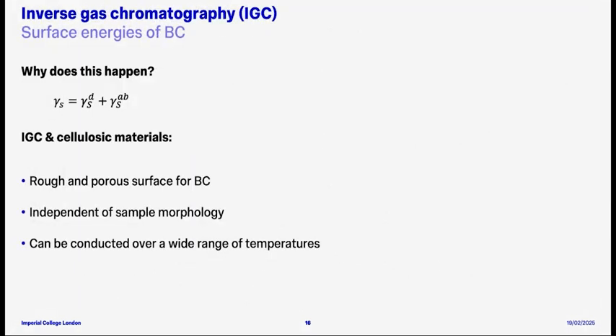So to investigate this observed difference in the quality of bacterial cellulose coating produced from different dispersing media, the surface energetics of bacterial cellulose was first quantified to ascertain its interaction with water and other organic solvents. So generally, the surface property of a solid is described by a dispersive and a specific component, where the total surface energy of a solid surface is the sum of the two.